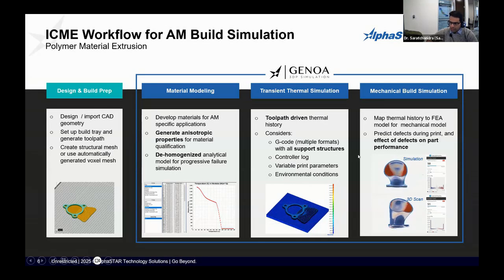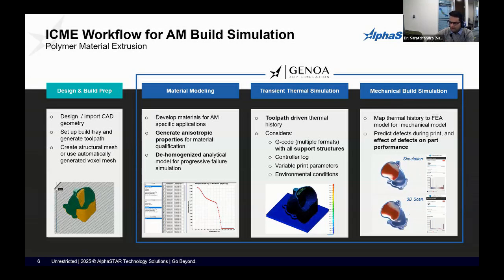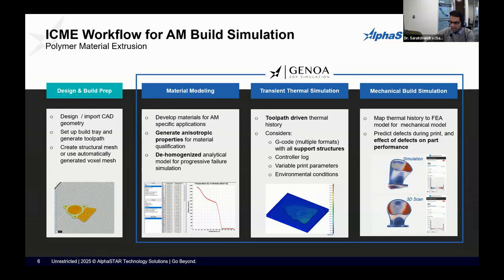Once you predict the thermal temperature that is happening at every stage of the print, we take that information and feed it into a mechanical build simulation, which is an FEM model for predicting the behavior of the part as it is being built. So we can then predict the deformations and residual stresses and damages in the part as it is being built, and then map that information onto a finite element mesh for applying in-service loading. So we can then perform your service analysis on a realistic part that incorporates all the build defects.